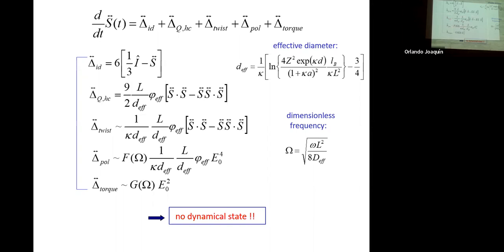And then you have a term which has to do with the interaction between the dipoles, and you have the torque contribution into the torque that the electric field exerts onto the core of the rod.